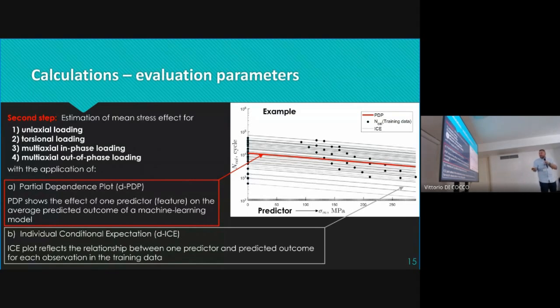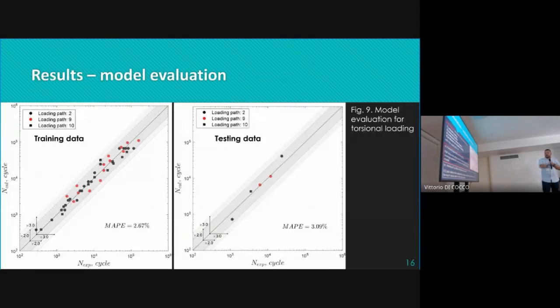So for each one, we have the gray line, and the dark red one is the partial dependence. It's basically an average value that shows the impact of the change of the static part of the stresses on the fatigue life. And further, first the model. This is on the left. You can see the training data for three paths with the average error of 2.67%. You can clearly see that most of them are within the 2 times boundaries. And on the right side, the remaining 10%.